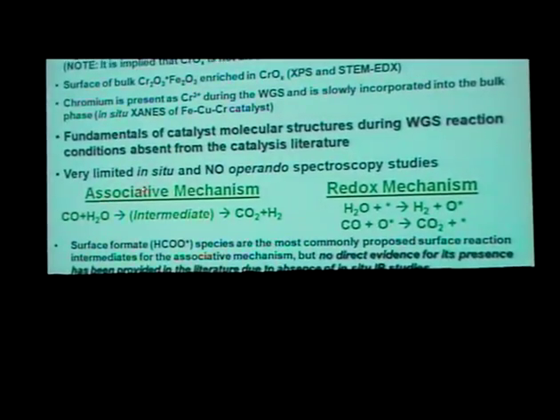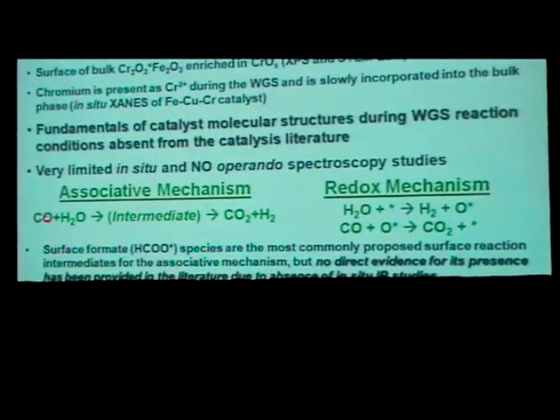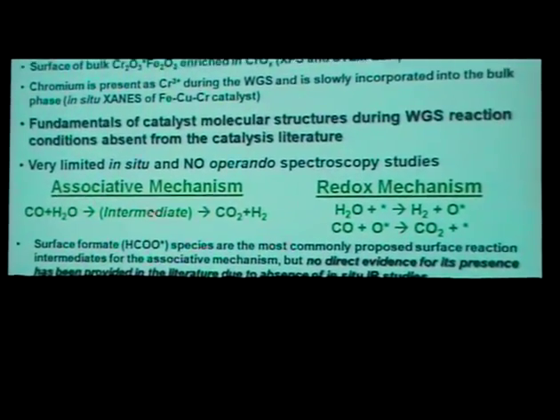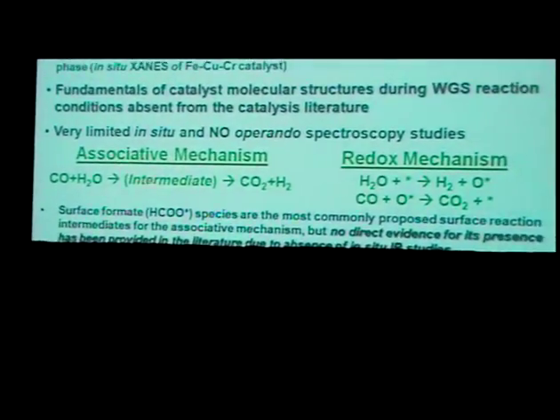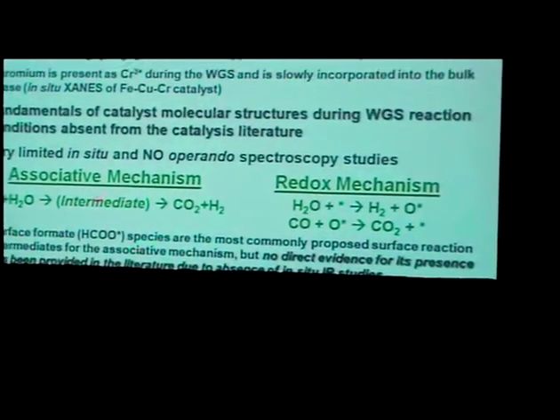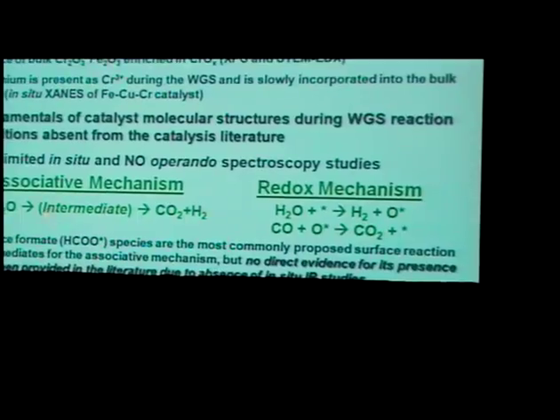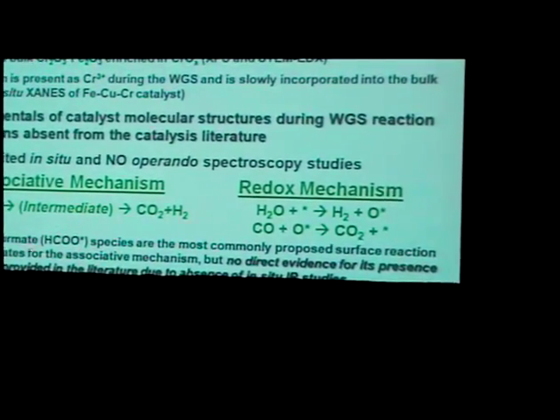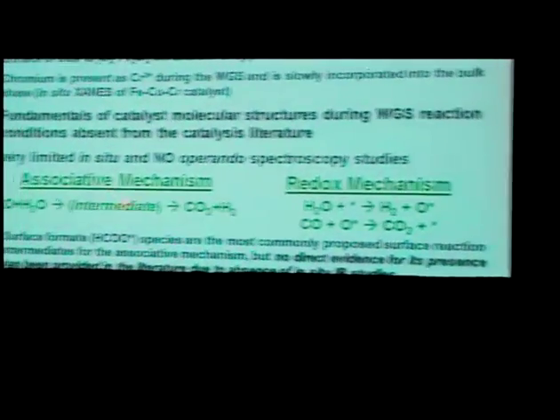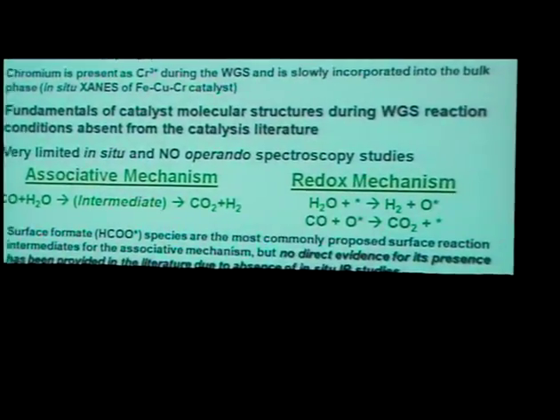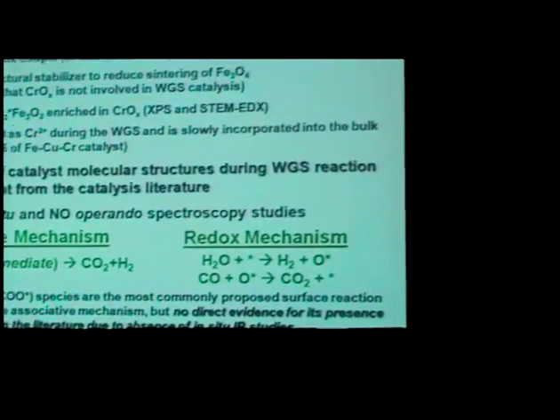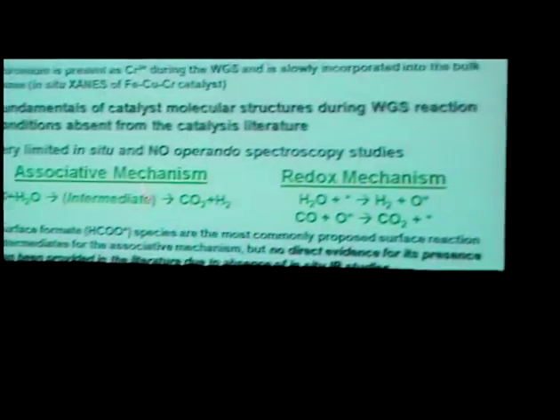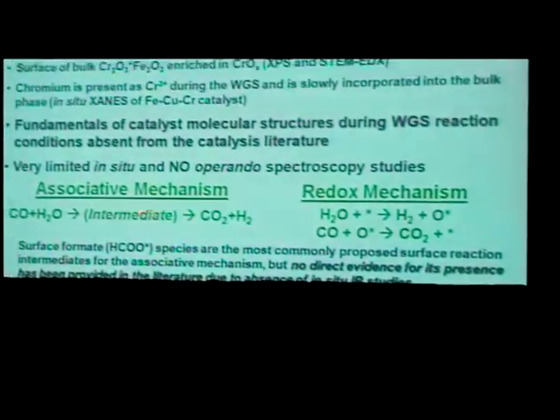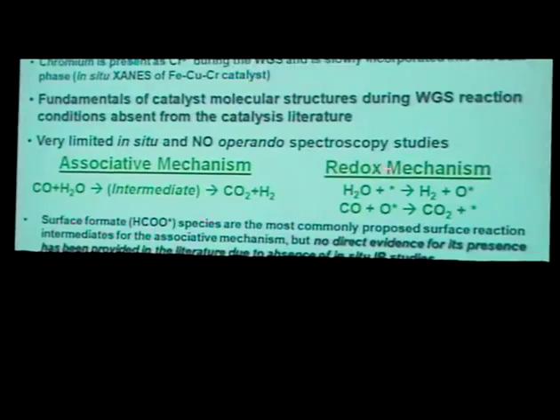And one is referred to as the associative mechanism, that CO and water react to form some intermediate complex on the surface. The most common intermediate people invoke is a formate intermediate. But there's no evidence supporting this. There's no direct evidence to show that this is the case. In fact, no IR studies have been reported in the literature to show this for these catalysts.